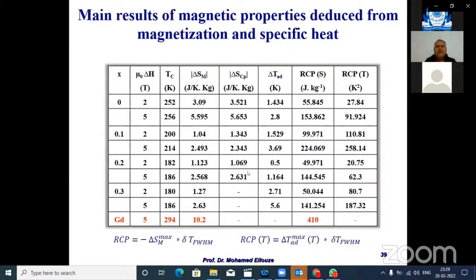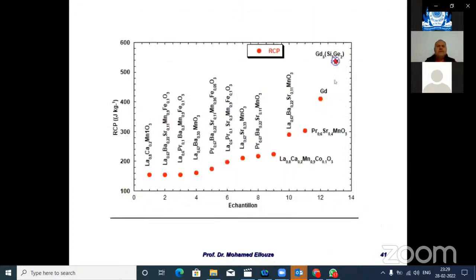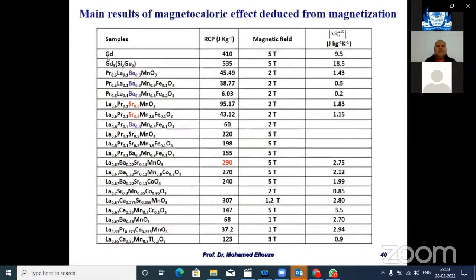Here are some results about the RCP, with gadolinium as a reference, and all the others are our samples. We can see that sometimes our RCP is very close to that of gadolinium, so we can improve this RCP using other methods.